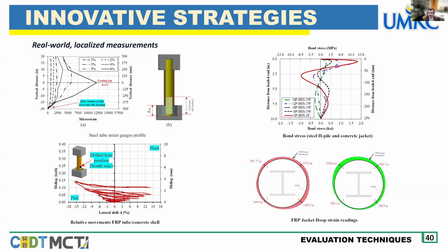As you can see, they are very important for us from the experimental test. For example, these are the readings for the strain gauges inside the steel tube, and they showed us that using the corrugated steel pipe inside our footing connection, the embedded length of 25 inches was efficient and sufficient in this case, because after 20 inches inside the steel tube, from the face of the footing, this is the face of the footing, there is no more reading in the strain gauges.